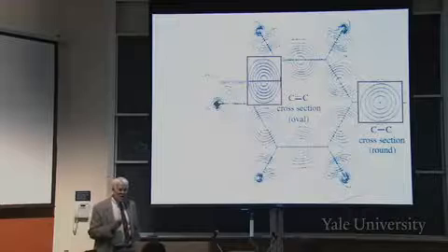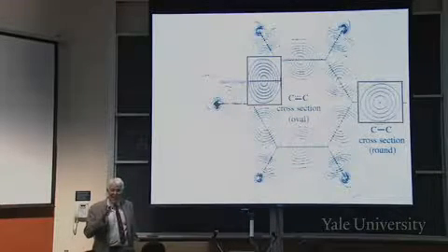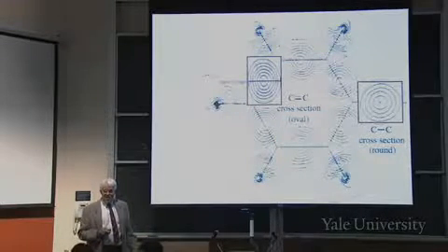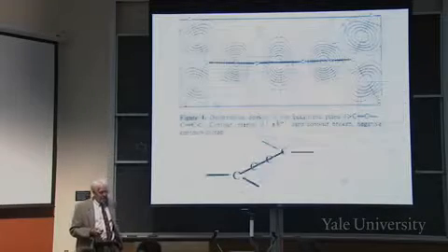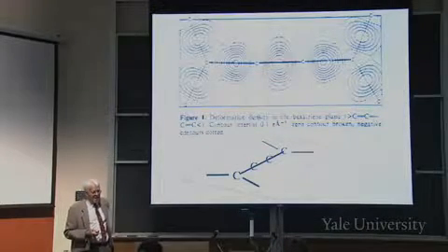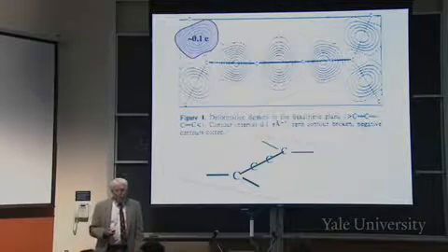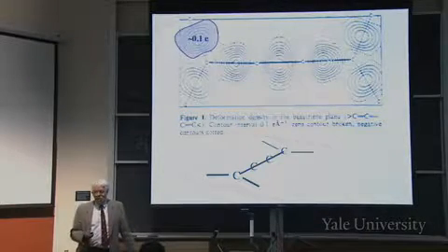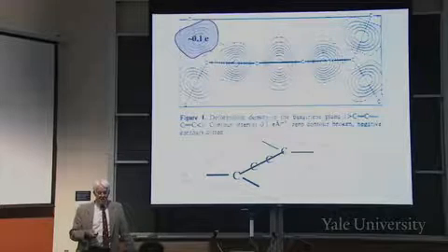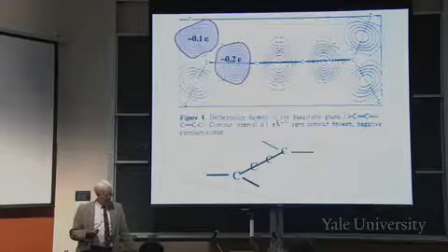Because they're partially made up of these p orbitals that point in and out of the ring, that distorts it from being round. Okay, now let's look at the double bonds that are in the middle of this molecule. First, that one, we've already seen that bond before, that was 0.1, had a round cross-section. But let's look at one of the double bonds.